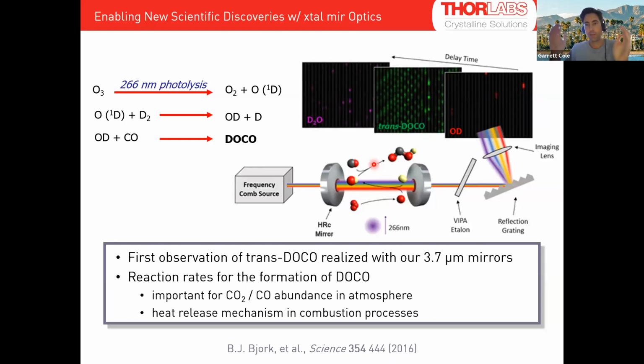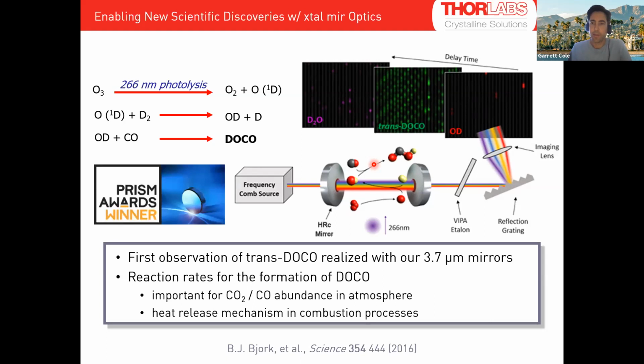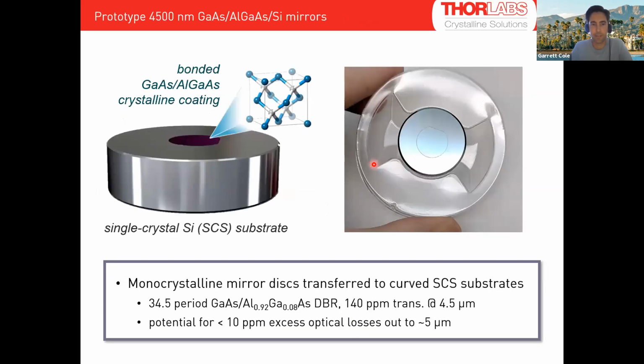They needed really high resolution, narrow line width cavity, which means they needed their optical losses as low as possible. So hence our mirrors were very useful there. So very cool academic output. We used this to leverage and develop a new product line, which are crystal MIR mirrors, and we ended up winning a Prism Award from SPIE and Photonics Media for that in 2017.